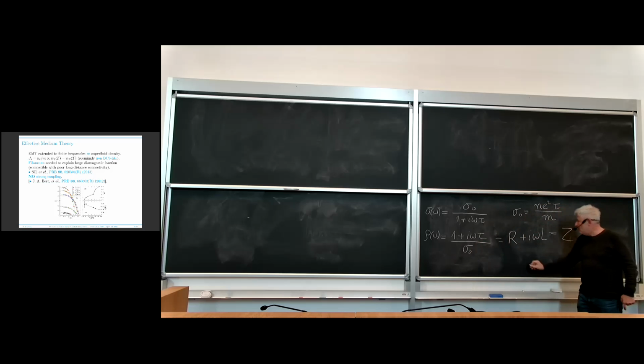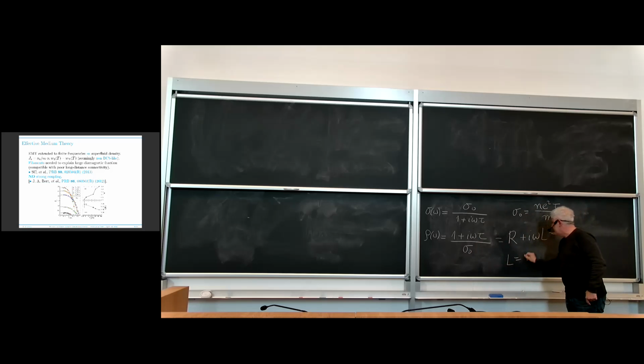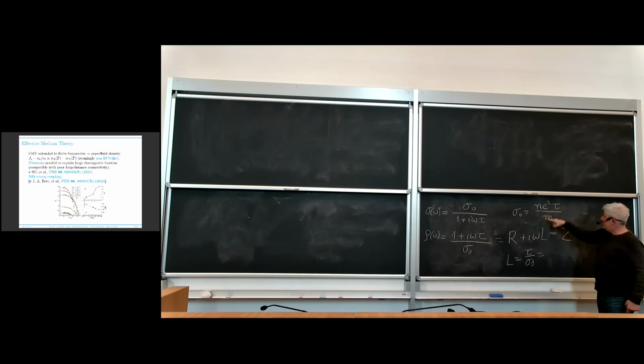More interestingly, the inductance is independent of the scattering time. So I write now my formula for the inductance. This is tau over sigma naught. And I read from this formula that tau drops and you have m divided by n e squared. Now, but for this trivial factor e squared, this is nothing but the inverse of what is called the superfluid stiffness, the ratio between the number of superfluid carriers and their mass.